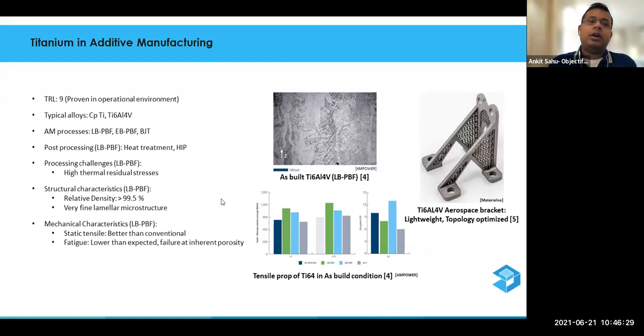So I'll take two examples, one in titanium, which is at technology readiness level 9. It is a proven material in the aerospace division, and it is in production for most end users and end customers. Typical alloys available are commercial pure titanium, titanium 6Al4V, which is grade 5, and an ELI grade, which is grade 23. You can process titanium in three different additive manufacturing technologies: laser based powder bed fusion, electron beam based powder bed fusion, and binder jet. Then you would require post processing such as heat treatment and hot isostatic pressing.